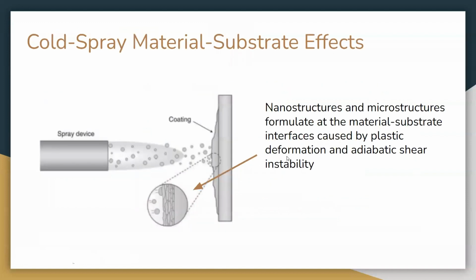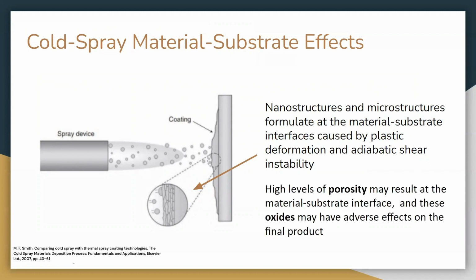So what happens when cold spray materials spray onto the substrate? For example, when tantalum gets sprayed onto a substrate such as aluminum or stainless steel. When the cold spray material sprays onto a substrate, nanostructures and microstructures can form at these material substrate interfaces, and this is caused by plastic deformation and adiabatic shear instability. Plastic deformation causes hardening mechanisms at the interface, such as work and strain hardening, and additionally, high levels of porosity can result from the interface characterization, and these oxides can have an adverse effect on the final product.